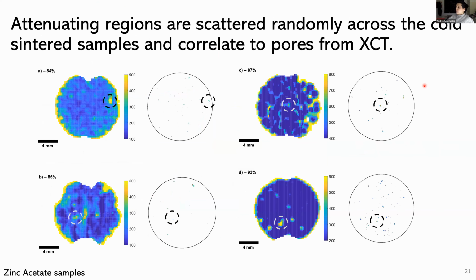So since we had done X-ray CT on all of the samples that were manufactured with zinc acetate as the liquid phase, we were able to do some one-to-one comparison of the features that we were seeing in the X-ray CT and the features that we were seeing in our ultrasonic maps. But I'm sure for those of you that have tried to do this one-to-one analysis, you're probably immediately identifying that there are plenty of features in the CT that are not necessarily being captured in the ultrasound, plenty of features in the ultrasound that are not necessarily showing up in the CT.